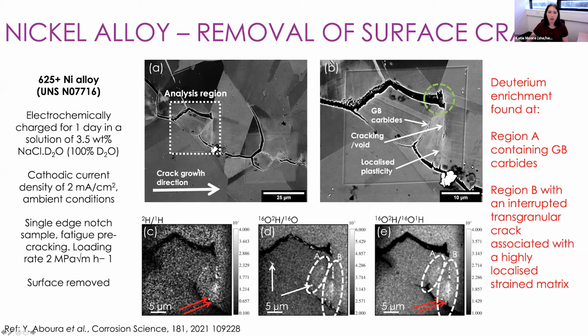Again, looking at our image in the SEM before we started doing the analysis, we can see this region here that crosses between these two cracks. We have grain boundary carbides along here, and we have a lot of localized plasticity in this region here. Again, no matter how we look at this image with different ratios, we can see we have very localized deuterium at the grain boundary carbides, and also again related to the localized plasticity here.